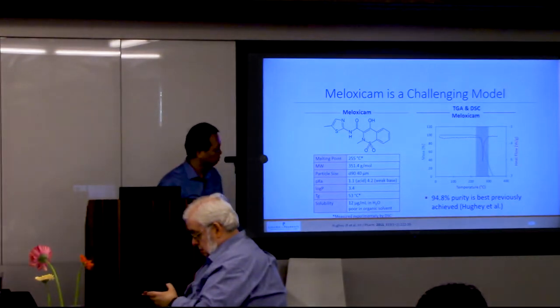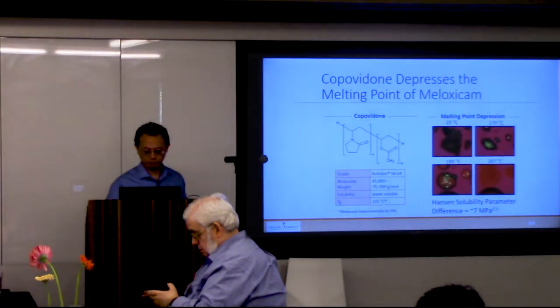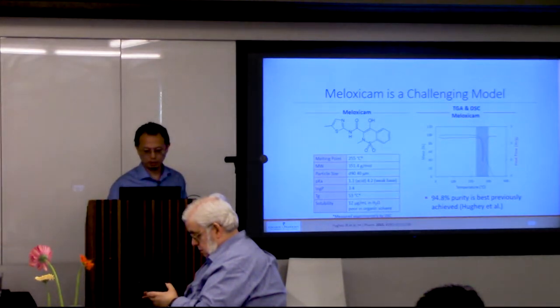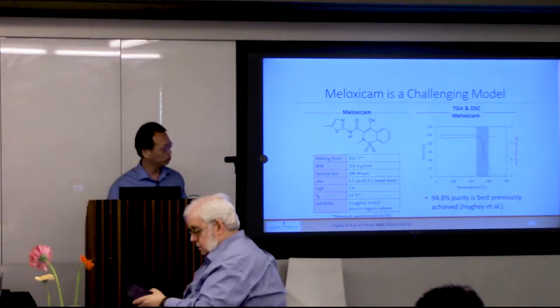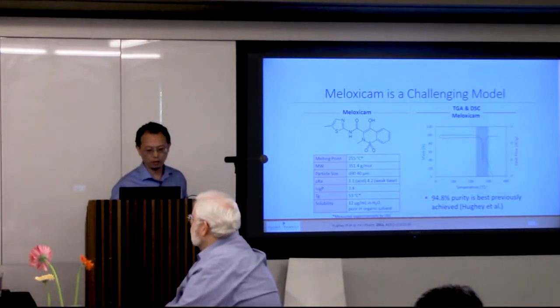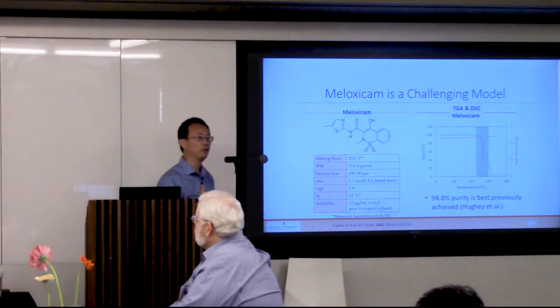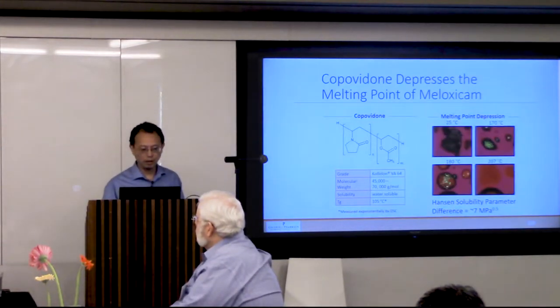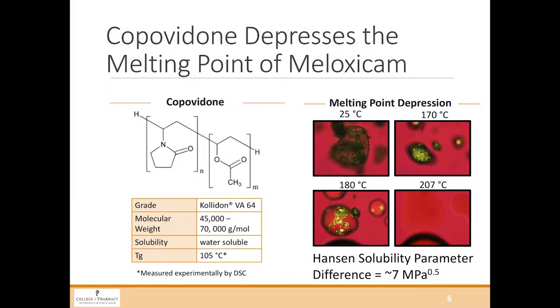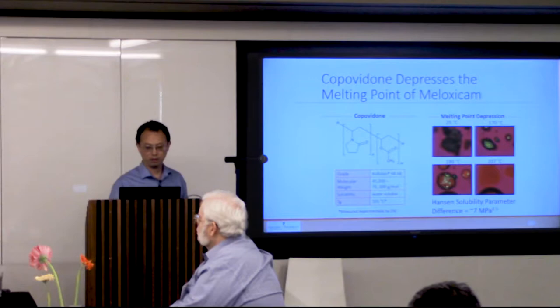Okay. So we see the melting point here on this DSC profile. This blue, this orange line. Once it melts, and this green line is the TGA profile, once the drug melts, it actually degrades. Now, what's really interesting with a composite, we have a significant melting point depression. If you look at this one here, the melting point is about 255, but even at 170 degrees, 180 degrees, the drug is already dissolving upon the melt. So because the drug likes this polymer so much, we can really rely on this melting point depression to dissolve the drug.